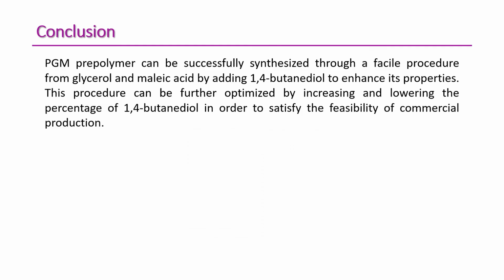And as a conclusion, PGM prepolymer can be successfully synthesized through a facile procedure from glycerol and maleic acid by adding 1,4-butanediol to enhance its properties. This procedure can be further optimized by increasing and lowering the percentage of 1,4-butanediol in order to satisfy the feasibility of commercial production.